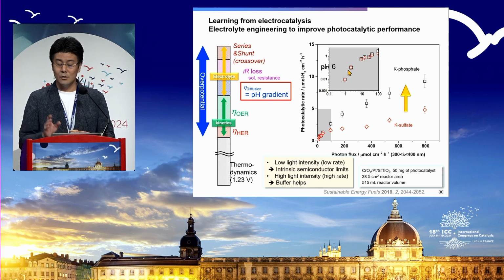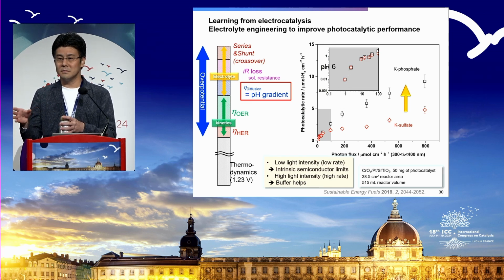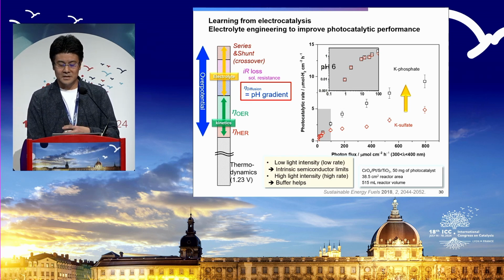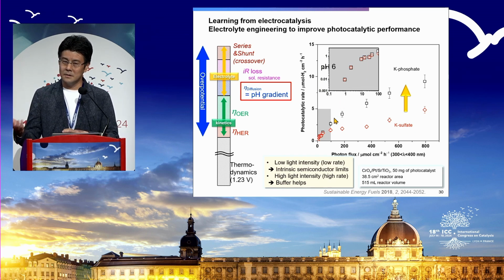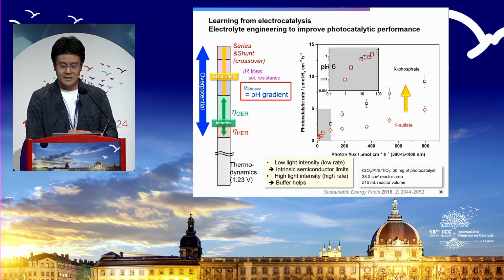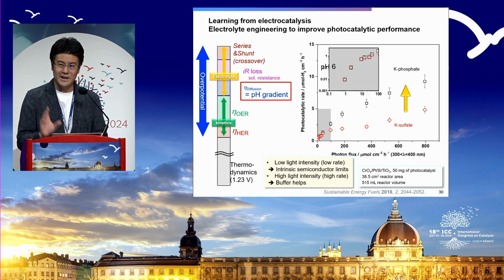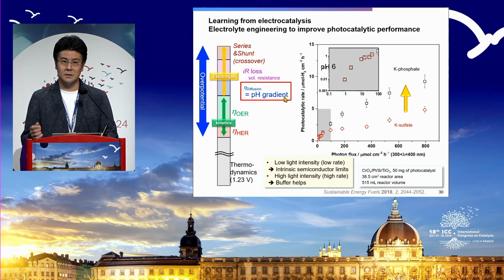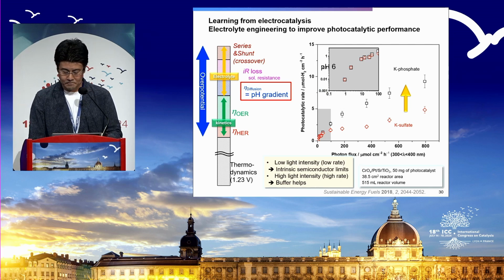So when you are working at low current density, this diffusion is not important. It matches between the sulfate and phosphate. If you increase the light intensity, for example, or your photocatalyst becomes much more efficient, you start to see the overall water splitting performance difference becomes larger. I think it's coming from this buffer contribution, reactant switching. So pH gradient is something that we need to start thinking about if you want to do this water splitting.